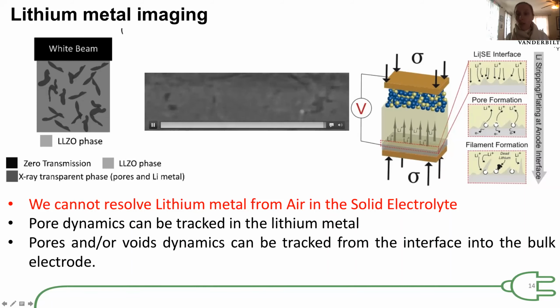And we're interested in tracking the lithium metal because non-uniform ionic flux or pores formed during stripping are thought to be nuclei for the formation of lithium metal. So if we can track the lithium metal, we potentially can start to answer or resolve some of these mechanistic questions related to lithium electrokinetics and how it changes against a solid electrolyte in comparison to a liquid electrolyte.